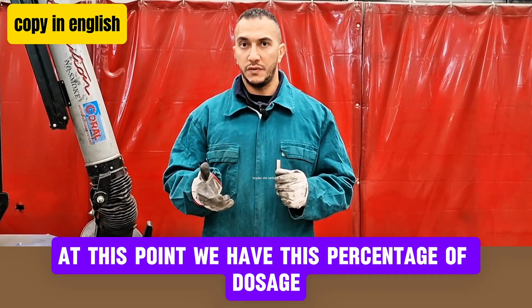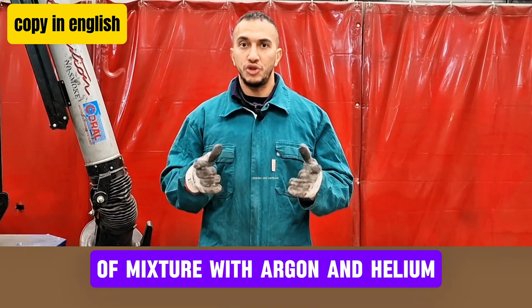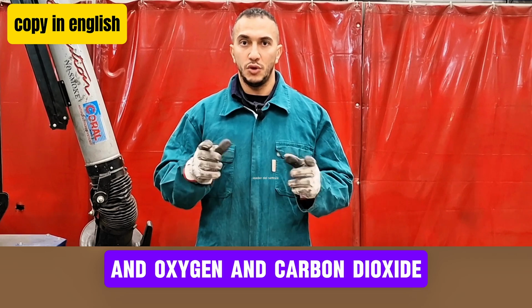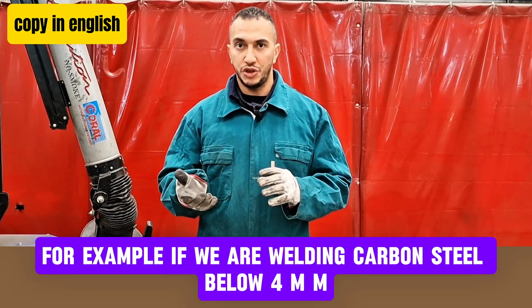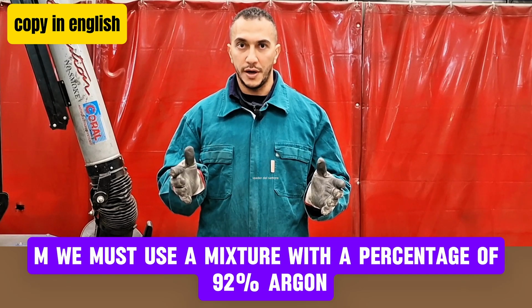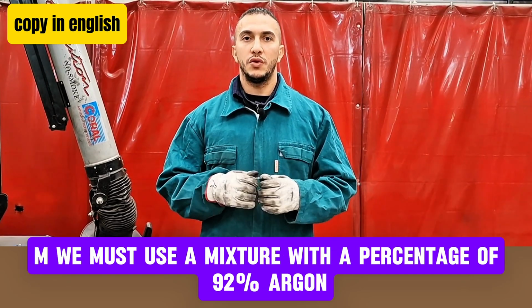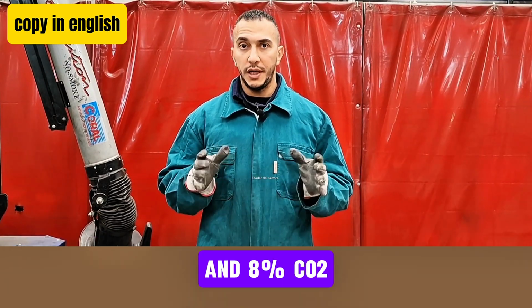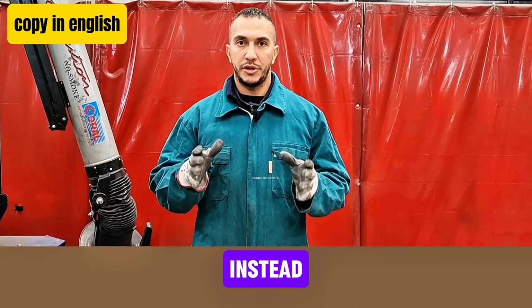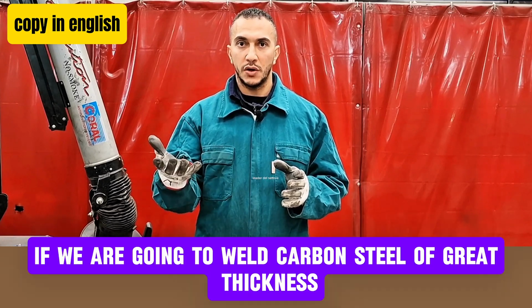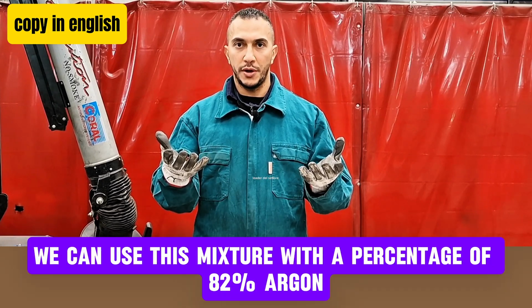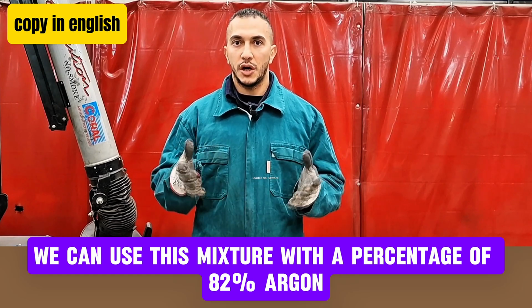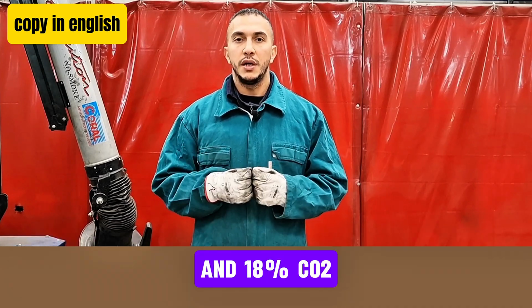At this point we have these percentages of dosage of mixtures with argon, helium, oxygen and carbon dioxide. For example, if we are welding carbon steel below 4 mm, we must use a mixture with a percentage of 92% argon and 8% CO2. Instead, if we are going to weld carbon steel of great thickness, we can use this mixture with a percentage of 82% argon and 18% CO2.